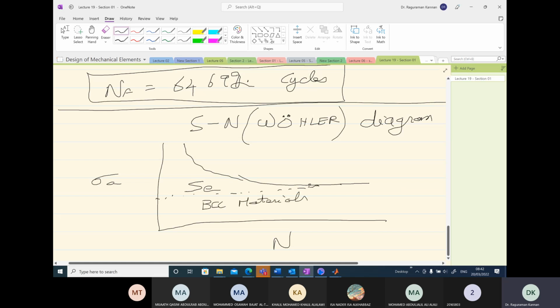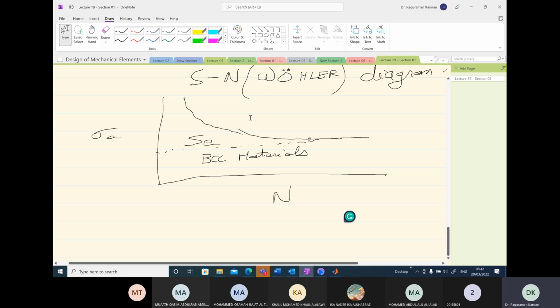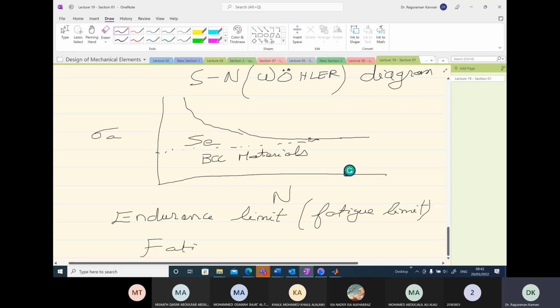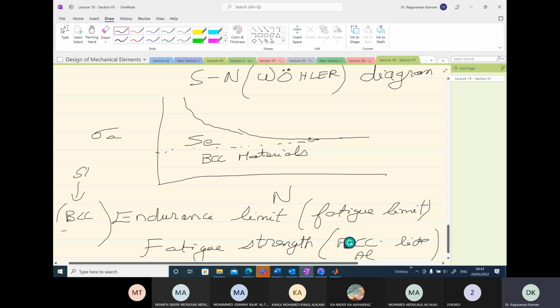For FCC materials like aluminum, we saw that we do not have an endurance limit. At least experimentally, we can show that endurance limit doesn't exist. On the other hand, what we have is a fatigue limit at 10 power 7 cycles or 10 power 8 cycles or 1 million cycles, whatever it is. And then we use that value. Again, it is important to understand the difference between endurance limit or fatigue limit. It is also called fatigue limit, and fatigue strength of the aluminum. Fatigue strength for FCC like aluminum, and endurance is for BCC like steel. For example, steel has BCC structure.